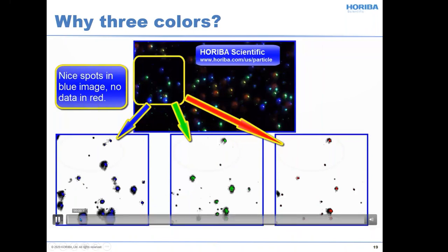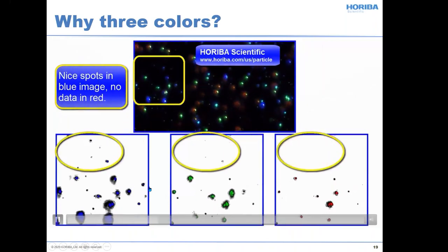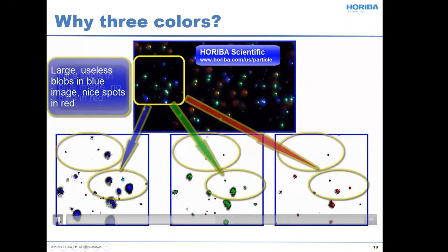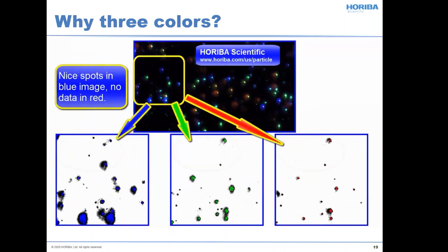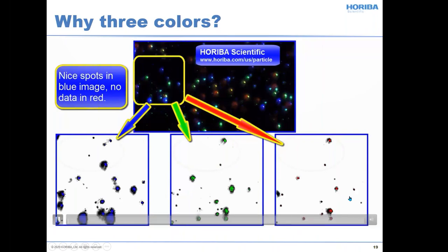If I look at the bottom of the frame, you can see these large, irregular blobs in blue — the camera is saturated. The whole name of the game is to find the particle. If I have a large irregular blob, I can't decide where the center is from frame to frame, so I have poor tracking. As I move to lower powers, I get nice, sharp points in the same areas. Those nice, sharp points make tracking easy, and when you make a computer problem easy, you get very good results.